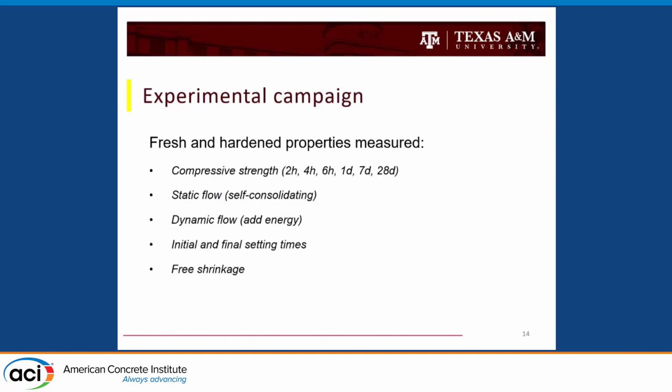We measured a number of fresh and hardened properties just for proof of concept. We looked at compressive strengths at different times. We looked at the static flow, which is basically the self-consolidating flow, and the dynamic flow when we're adding energy, so we can see if the mix is thixotropic, so it's not moving when we remove the cone, but then we add energy, it's spreading.